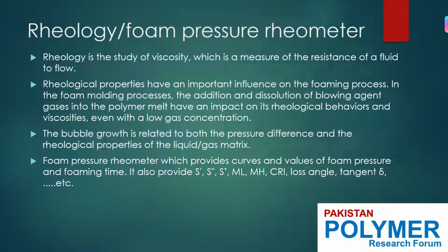Also, viscosity is a measure of rheological properties of a fluid which deforms when stress is applied. Shear viscosity is a viscosity coefficient when shear stress is applied, while the extensional viscosity is the viscosity parameter when extensional stress is applied. The rheological properties have an important influence on the foaming process. Like in the foam molding process, the addition and dissolution of blowing agent gases into the polymer melt have an impact on its rheological behaviors and viscosities, even with a low gas concentration.